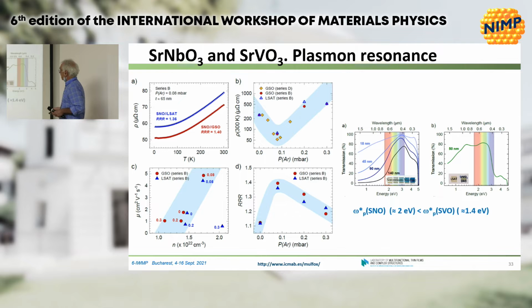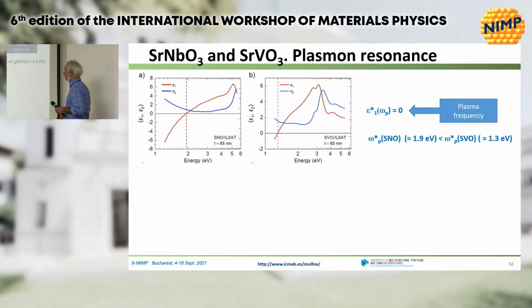First, obviously, we determined the plasmon resonance for all the films, measuring the ellipsometry, and we determined the transparency, we did everything. So that was clear, that we had the crossing epsilon 1 equal to 0 at the plasma frequency, that was the edge of transmittance, or the reflectance, so that was good.